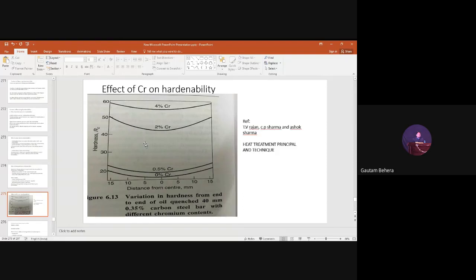Because the depth and distribution of hardness is not the same everywhere, because of the formation of more chromium carbides or strong carbide forming elements, which are basically not dissolving into the austenite easily. And even if they dissolve, the homogenization of austenite is not happening easily. It is taking much time. So this is the answer.